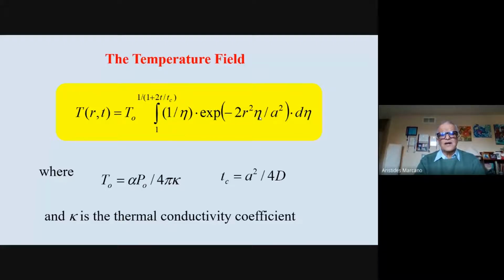So the important thing here is just we have this temperature amplitude. That temperature amplitude is given if you have a continuous light there. So it's proportional to the power of the light, P sub 0, and also to the absorption. But this absorption, we can consider that this is not actually the loss in the sample, because the sample can have some scattering, it can have some fluorescence, some phosphorescence, some Raman, and those effects actually impact the transmission of the sample. But I'm talking about this alpha as just the thermal absorption. It's the absorption related to the heating that produces the heating of the sample.